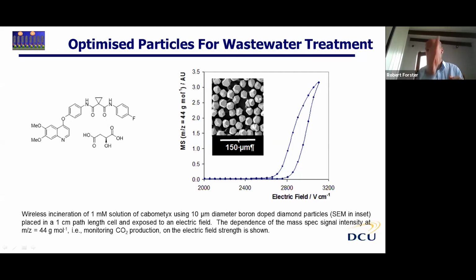We talked about the exponential decay that can occur depending on electrolyte concentration close to a conventional electrode - the same thing can happen here. What you're looking at is mass spec data from the headspace of the reactor as a function of electric field strength. We're looking for 44 grams per mole, which is CO2. In the presence of the Cabometyx, at low field strengths you don't get any carbon dioxide, but approaching about 2,500 volts you suddenly see the appearance of carbon dioxide.